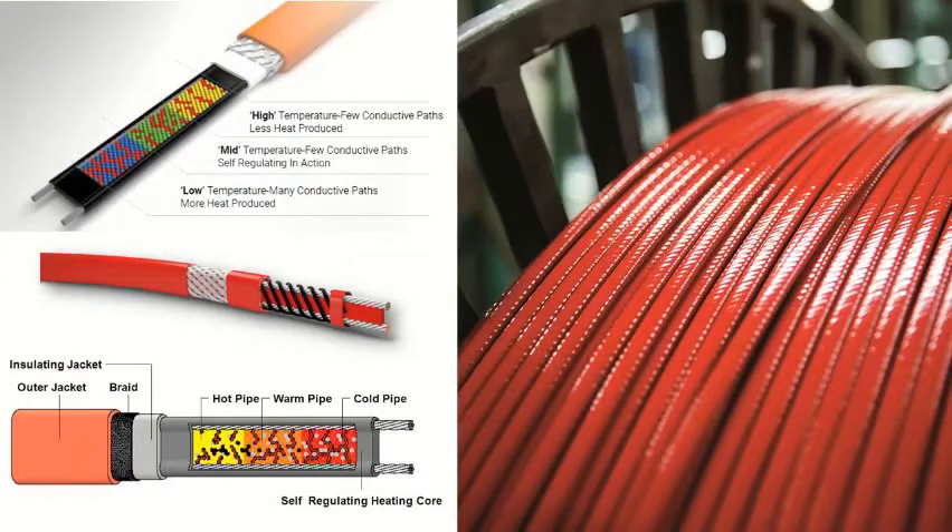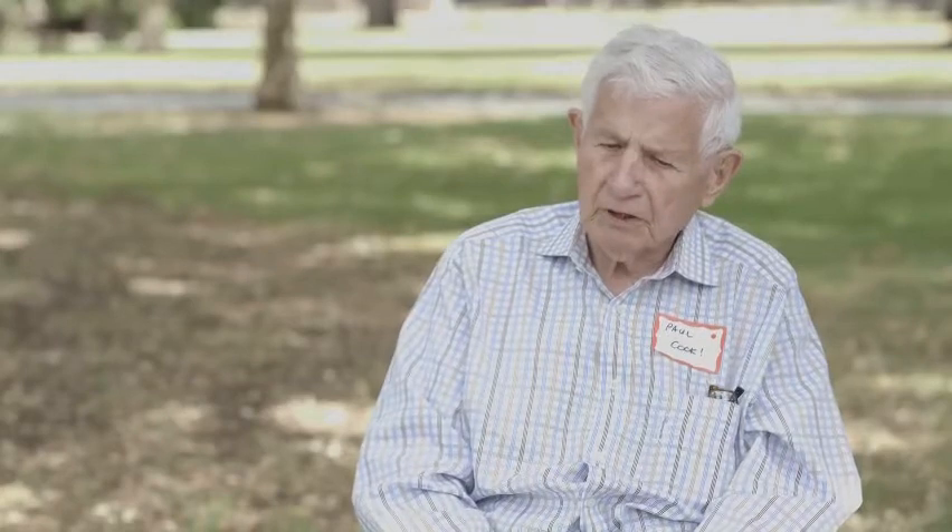The result of the combination of the Chemelex technology and the Raychem technology was to have automatic control of the heat output and the temperature. By having the crystalline melting point of the polymers be at different temperatures, we could adjust to automatic self-regulation of heaters. And it worked brilliantly for the hundreds of products that we made from it.